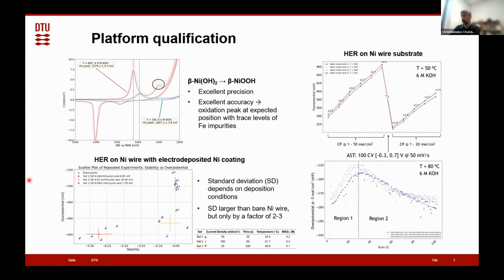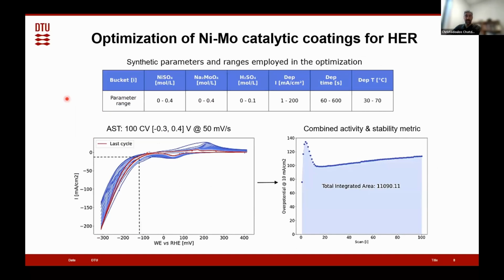Finally, we investigated the reproducibility of the platform when we do electrodeposition of nickel on a nickel wire. And again, although the standard deviation is slightly larger than that of a nickel wire and somewhat dependent on the actual deposition conditions, here we have 5 repetitions for 3 different sets of deposition conditions listed here. In all cases, the standard deviation is quite small and more than adequate to employ the platform for optimization processes with electrodeposition. So being convinced that the platform is functional, we attempted the first experiment where we tried to do optimization of nickel molybdenum alloy catalytic coatings for hydrogen evolution in alkaline environment.